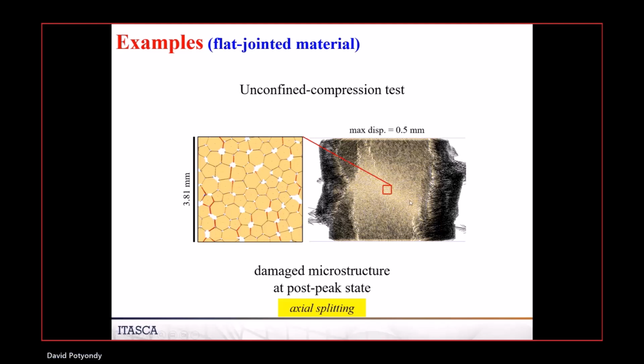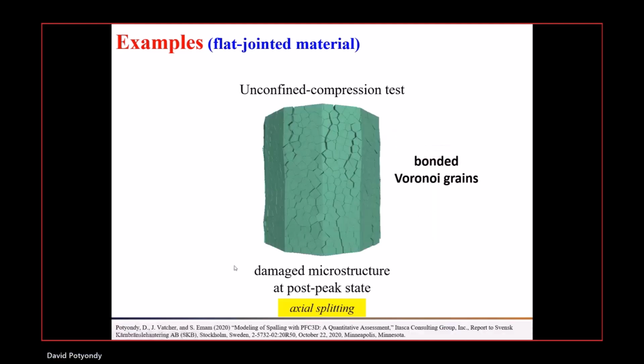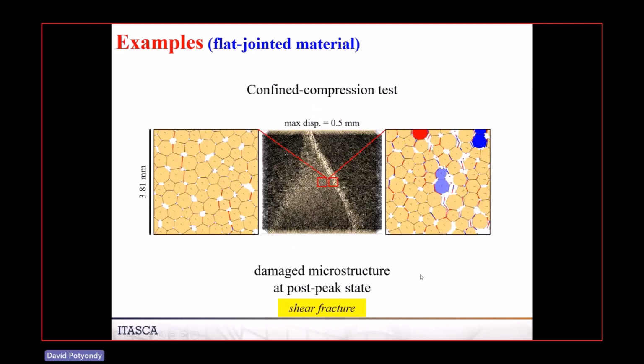The other interesting, powerful thing is there's all kinds of complicated stuff going on inside the material. This is the damage, and this again is after the peak. And what you're seeing is very complex damage in here. You're seeing partially broken things. Again, thickness is proportional to the amount of opening. And so you're seeing these regions that have fully failed, these edges of the boundaries of the grains, right? The same sort of thing happens if you do the bonded Voronoi grains. We've seen this one as kind of a funny slide before, where you're getting that axial splitting.